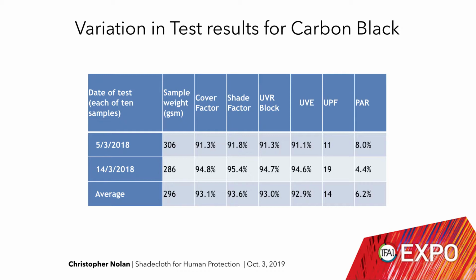Now that's partly due to the fact that they cut a piece out of this material, a small piece, and weigh it. And it's not always cut accurately. And the fact that if you're weighing a piece about this big on a scale and trying to attempt to work out what the grams per square metre is, the error of measurement is very, very significant.